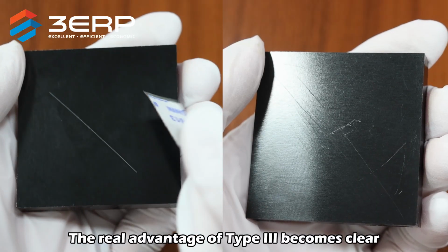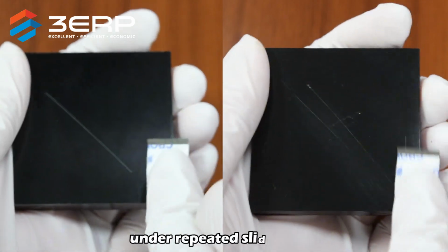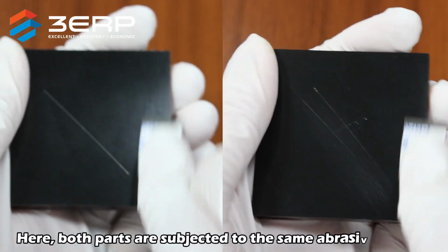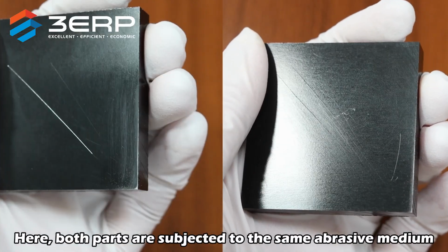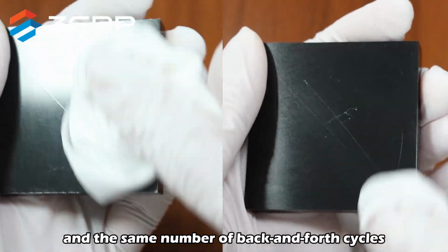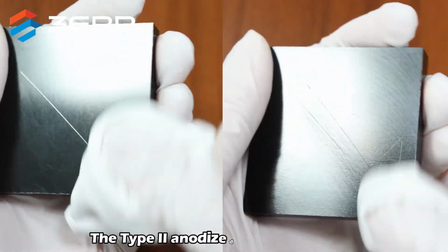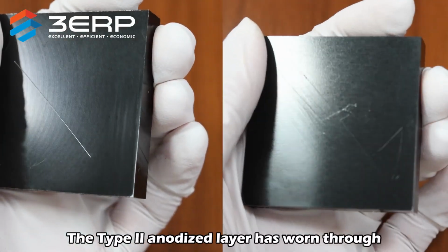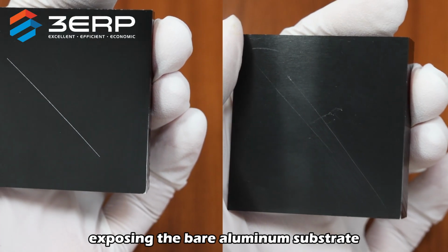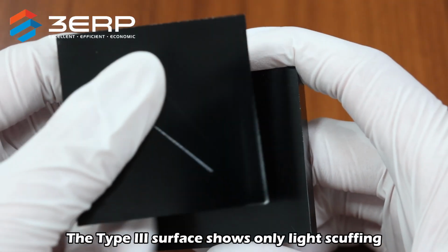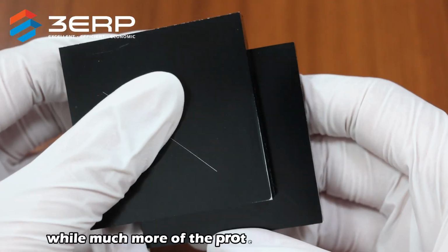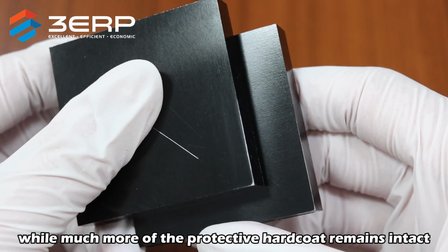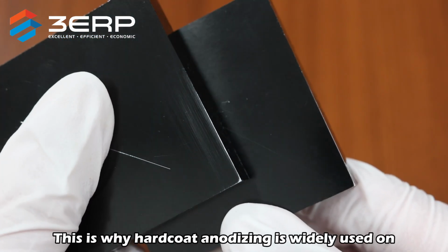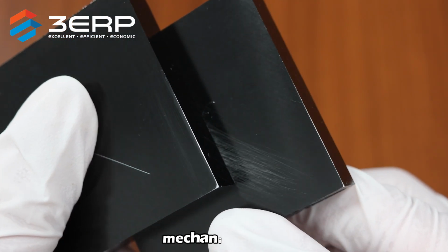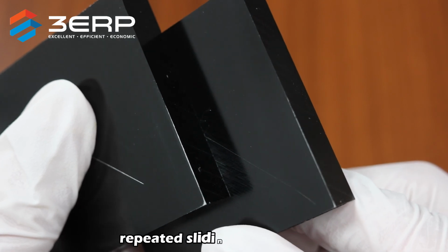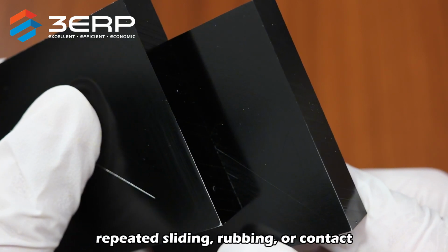The real advantage of Type 3 becomes clear under repeated sliding wear. Here, both parts are subjected to the same abrasive medium and the same number of back and forth cycles. The Type 2 anodized layer has worn through, exposing the bare aluminum substrate. The Type 3 surface shows only light scuffing, while much more of the protective hardcoat remains intact. This is why hardcoat anodizing is widely used on mechanical components subject to repeated sliding, rubbing, or contact.